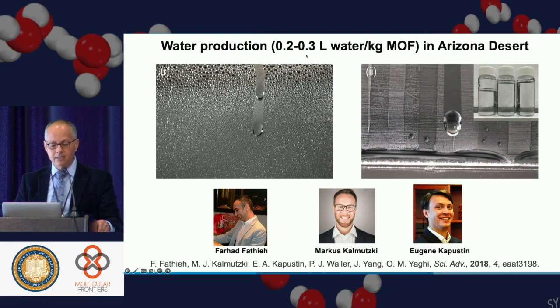We collect about a cup of water per kilogram of MOF. Okay, it's not optimized, but it shows I can, in the Arizona desert, where the humidity in this case was 30%, collect water from the air and generate a cup of water. If I want 2 cups of water, I could use 2 kilos. I think the powerful thing here is that you're generating water without energy input aside from ambient sunlight. I'm not electrifying this at all.